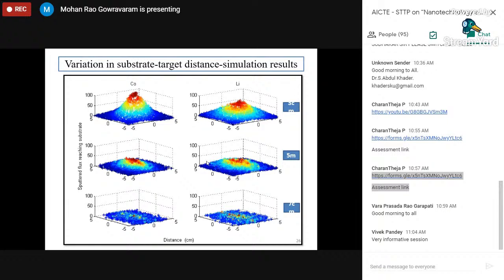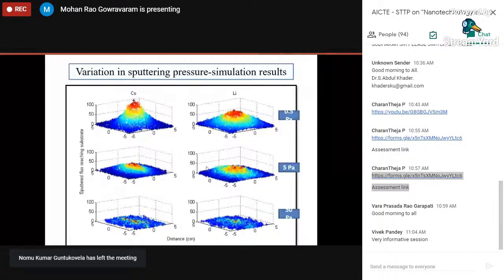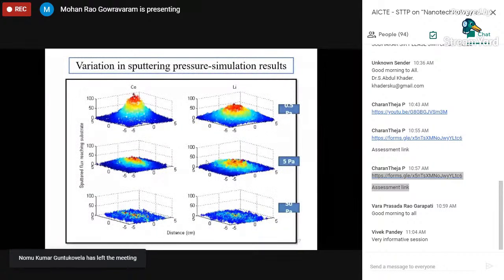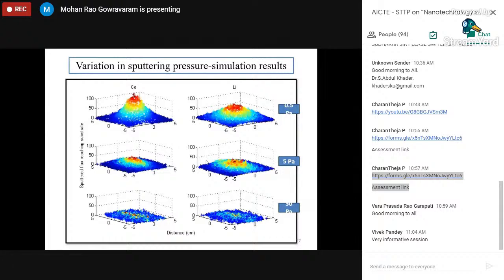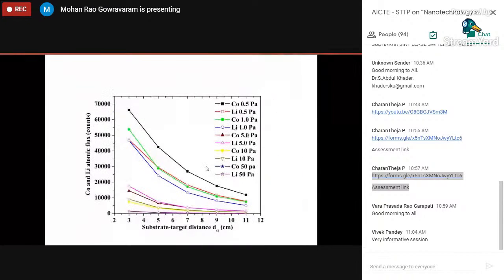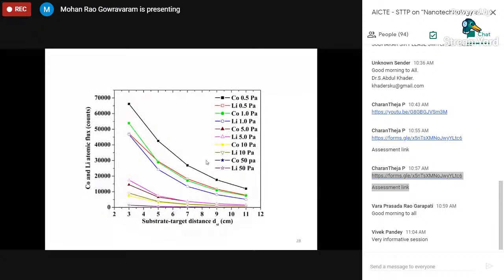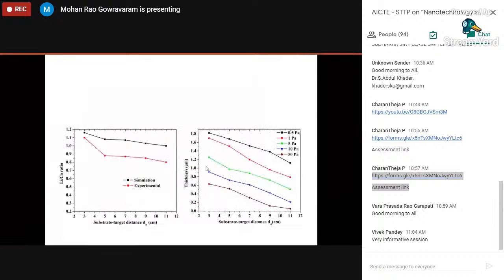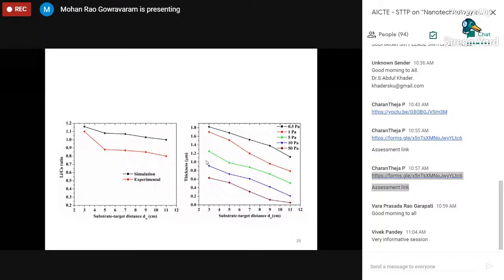In the literature, it was mentioned as 10 centimeters. And if you put 10 centimeters, nothing will come. The optimum distance is 4.5 centimeters. Similarly, you simulate what happens when you change the pressure. You come out with some pressure data where you see all the elements present in your film. So you use this target to substrate distance and this pressure and deposit thin films, and then you find out what is the cobalt and lithium atomic ratio, and then you optimize the process parameters.